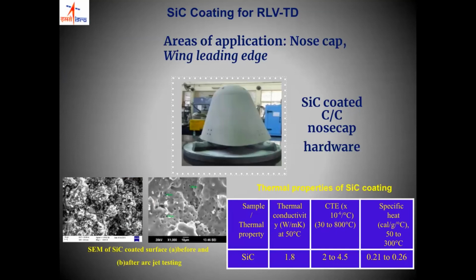There we have to use a different material, which we call a carbon-carbon composite. And that carbon-carbon composite is very prone to oxidation. So a special coating based on silicon carbide was developed, and finally they were tested and qualified for this application. This is the detail of that coating over the nose cone of your carbon-carbon composite.